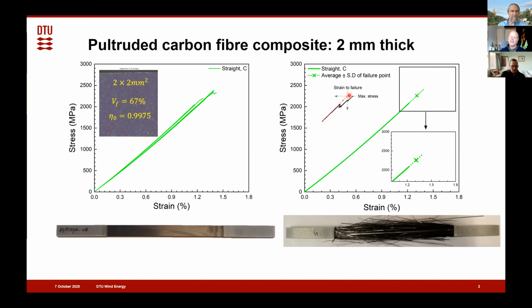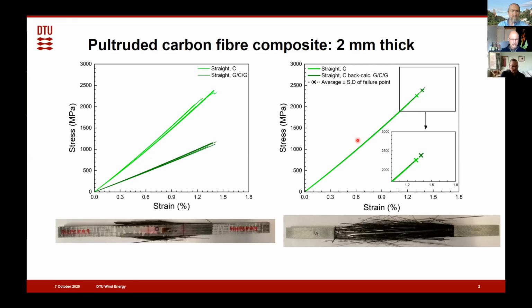And here the strain to failure value is defined as the point for max stress, but where we are ignoring this local failure happening before the max load point by doing a polynomial fitting of our tensile curve. So this test here is then going to one line here, and then we have the scatter of the different samples and the mean value of the stress strain curve. We can then, inspired by Wisnom and co-workers' work, now do the same rectangular sample, but now with a reinforcement layer, where we are replacing the tab material with a ply of glass fiber and make this as thick such that it will survive the failure of our test sample. So now this is the green curves here, where we have the stresses of the complete test sample.